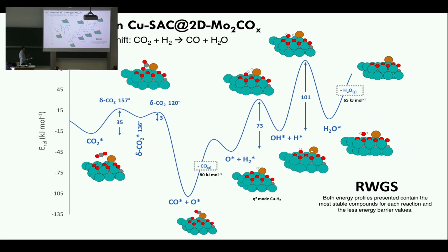Okay, the system is not actually very selective towards methanol. It's highly active, but not selective. So that should mean that the routes towards CO shouldn't be difficult, at least. And actually, if you adsorb CO2 on this interface and you cleave it, you see that the barriers are very low. You can form CO easily, and that competes with pure methanol hydrogenation. Of course, to know the main composition or the ratio, you would need to construct a kinetic model. I don't know if we will do it, but in any case, at least on a qualitative level, we can first know the nature of the site and then rationalize the catalytic activity that is found experimentally.